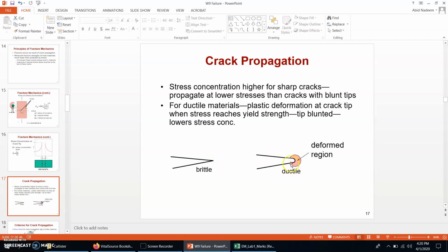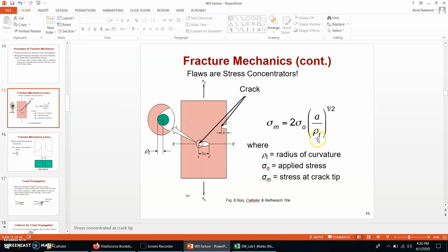But in the case of the ductile material, there will be plastic deformation, so the area at the crack tip will increase, and the radius of curvature for the crack tip would also be greater. If I go back to this equation over here, the radius of curvature for the crack tip will be greater for the ductile material. Therefore there will be a lower amount of stress at the crack tip. So the stress will reduce at the crack tip for the ductile material, but for the brittle material, there will be higher amounts of stress over here.